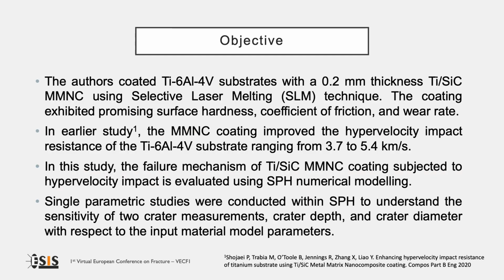The aim of this work was of developing a numerical model for predicting failure of the titanium silicon carbide metal matrix nanocomposite, exploiting the SPH technique. The results of the hypervelocity impact test already performed by the authors in the earlier study are exploited in this work. Using selective laser melting, a titanium silicon carbide metal matrix nanocomposite coating with a thickness of 200 microns was deposited on a titanium 6-4 substrate.